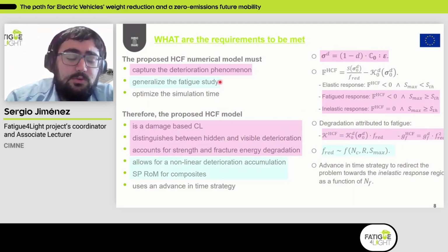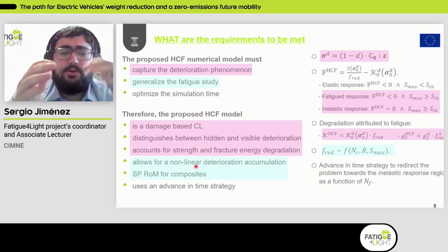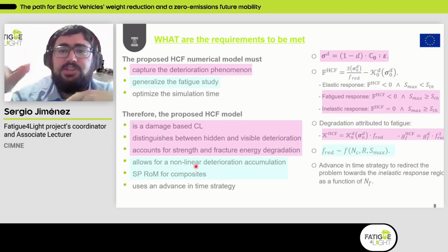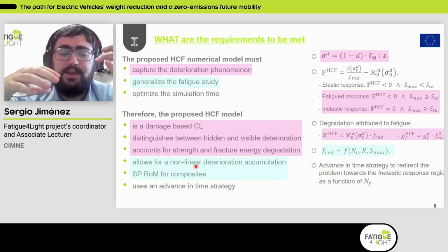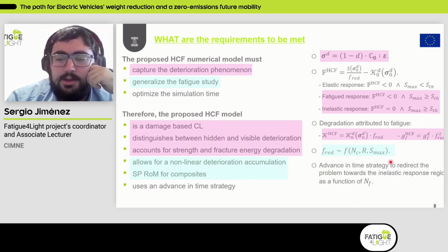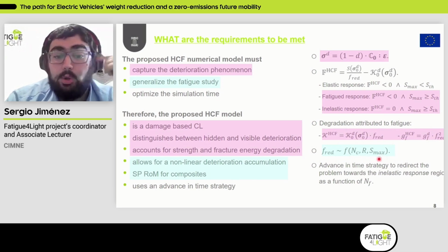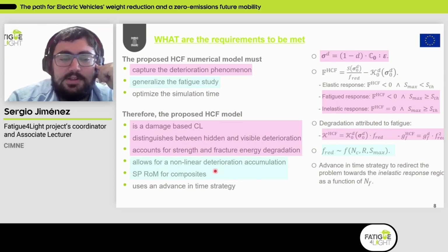Then we need to define a model that is able to generalize the fatigue study, in the sense that we need to account for nonlinear deterioration accumulation. So we need to make sure that if we change the load conditions, then the model itself readapts to obtain the corresponding response in the material. And we do that by defining this reduction function that I was mentioning previously, not only as a function of the number of cycles, but also as a function of the load being applied, described through this stress ratio and the maximum stress. So changes in the load itself induce changes in the degradation path followed along the simulation. And of course, at the composite level, what we are using there is a series-parallel rule of mixtures approach, where we focus the attention at the composite level. Sorry, not at the composite level, but at the component level.